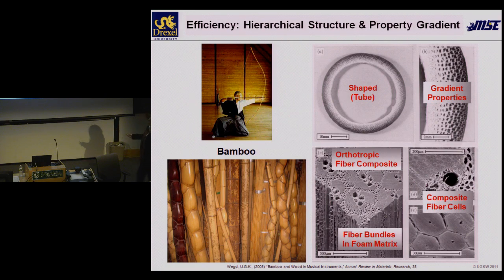When you look at bamboo, of which there are about 1,300 different species — there are always species particularly suited for a given application — you find it is a combination not only of the material from which they are made, which is a cellulose-based composite, but also how they're structured. Coming from top down: the bamboo grows as a hollow tube, which gives it efficiency. There's a property gradient — the fibers are unevenly distributed across the section. Each fiber is a bundle arrangement protecting the tubes that feed the plant, with highly elongated fiber bundles in a matrix. Each individual fiber is itself basically a plywood-like composite material — this is why these materials are so efficient, because they have hierarchical structures.